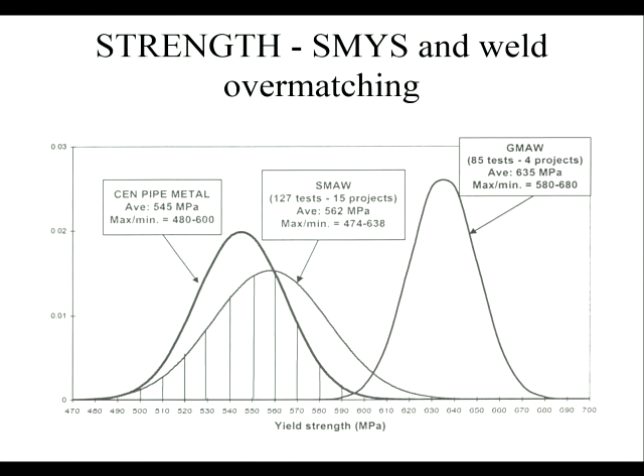So you don't do that based upon the minimum. So here's an example. So this curve here, the heavy curve here, is the pipe material. This is a shielded metal arc weld. It actually is stronger than the pipe material, but if you picked a part of the weld distribution down here and you picked a part of the pipe distribution up here, the weld would be weaker. This situation here, this case, the distributions are separate, and only in this little area here would you worry about overlap. So this one is correctly overmatched, and this is the one that you would specify. This one here is overmatched, but it's not correctly overmatched, and you wouldn't specify that. So you need to know the distribution of strengths to fully choose the correct set of welding parameters, because you want the weld to be stronger than the pipe for the best performance overall.